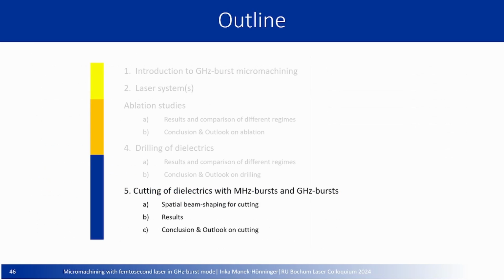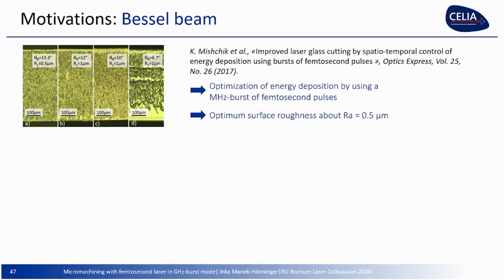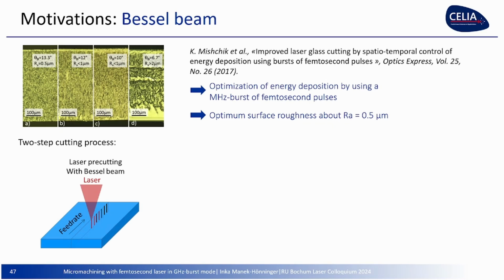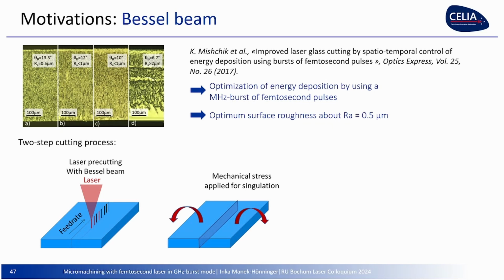which is shorter, on cutting of dielectric in megahertz and gigahertz burst regime. So cutting has already been shown with megahertz burst. There were 4 pulses within the burst. It's an old work also of the Lopez and Konstantin Mischik, who was a postdoc at that time. And it is a 2-step process when you do it like this. Actually, with the Bessel beam, you do a pre-cutting, and then you need some mechanical stress or heat to separate